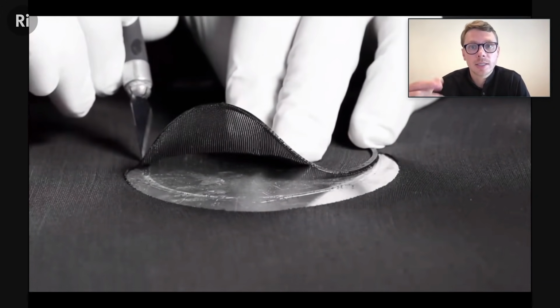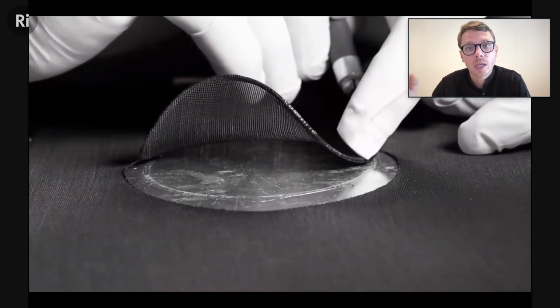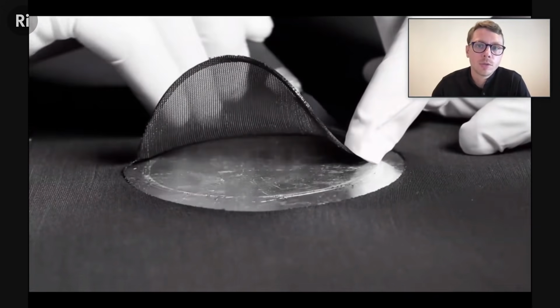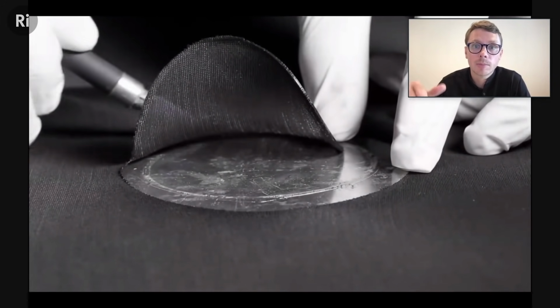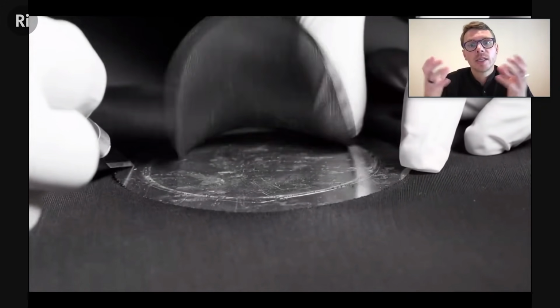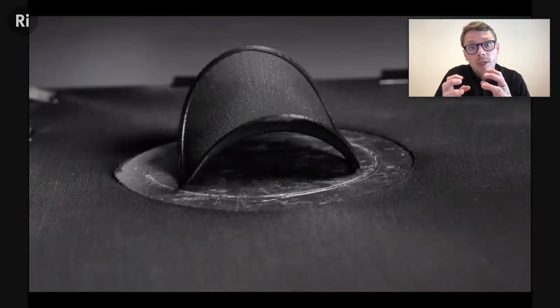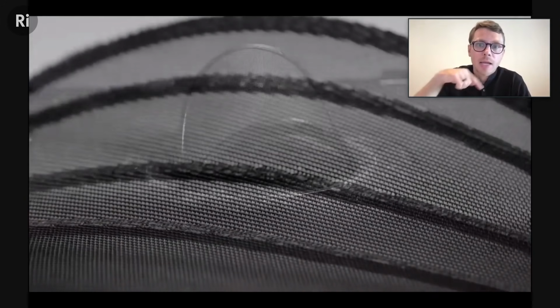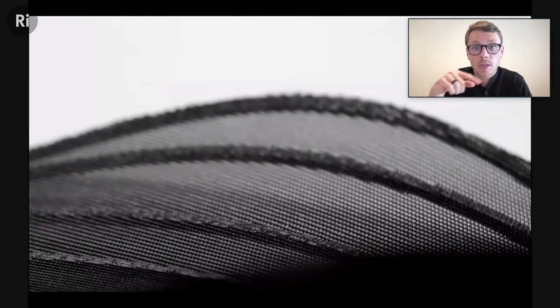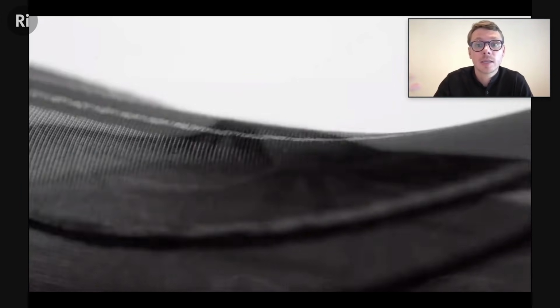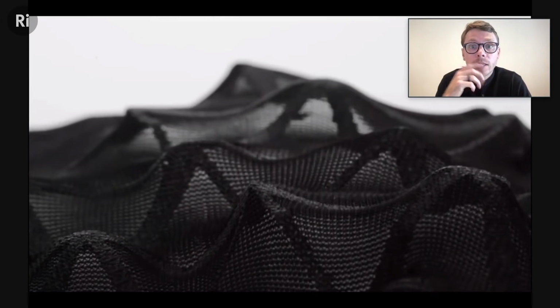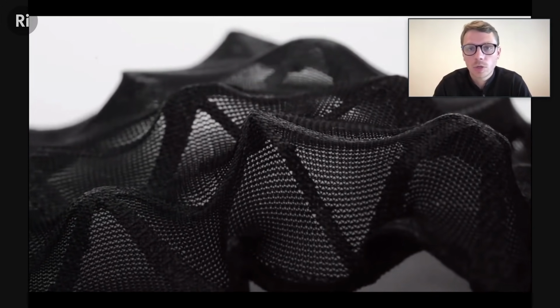So when you release it, in this case, when you cut it out, a circle jumps into a saddle shape, a hyperbolic paraboloid. So it goes from flat to 3D simply by the force of the stretch and the pattern of the printed structure. So that constraint pattern dictates the structure that you will get, like pleating or tufting or rolling or curling.